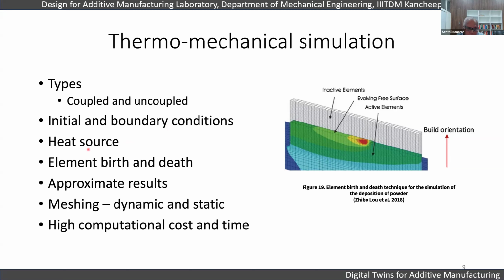Normally, lasers and electron beams are used in powder bed fusion. So lasers are typically modeled as a Gaussian beam, having full width at half maximum, which has a maximum peak intensity at 1/e or 1/e² from the tip of the maximum intensity. And many times they use element birth and death, which is a very old concept, which has been used in many different approaches. One of the biggest drawbacks is you get an approximate result, because all these are numerical methods.